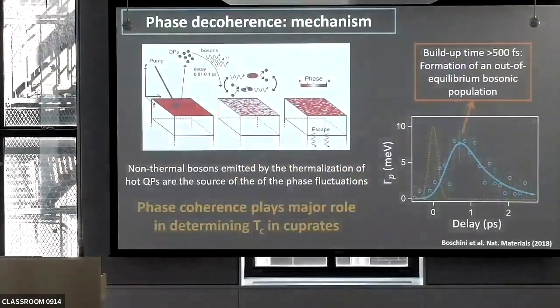The simple model we put forward, well, for one thing is we have a superconductor. Here, wait, hang on a second, Andrea. Yes, sorry. How does it depend on fluence? So my big question would be, could I have two regimes depending on the fluence? Once I just mix the phases, and second time I really destroy the amplitude. Possibly. So there are two fluence regimes that Fabio has explored. I'm showing you the low fluence regime.